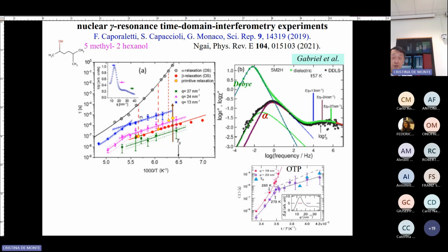You can do it by dielectric too. So with dielectric, you can see the alpha relaxation and the JG relaxation. This is monohydric alcohol data here, but they did it for many materials, like ortho-terphenyl, which is a molecular glass former. They did it for polymer. These are very recent advances, and even for CKN, calcium potassium nitrate. So all these are very important, but they are microscopic. When you find them at different Q, or different length scales, they are very local.